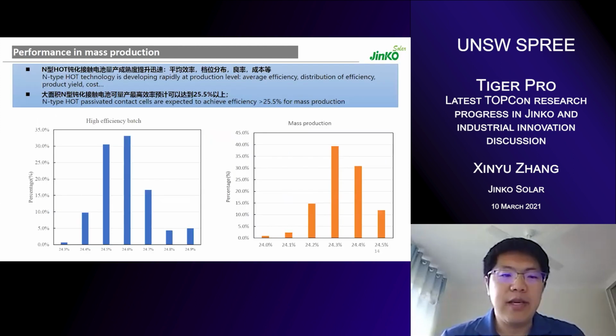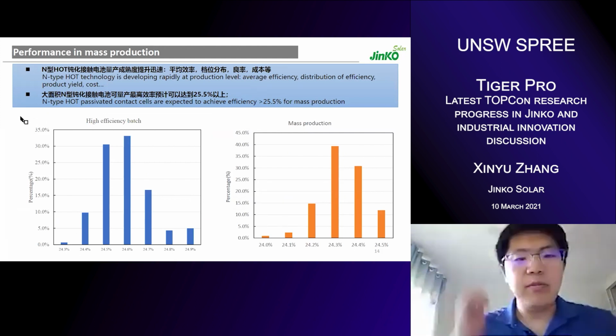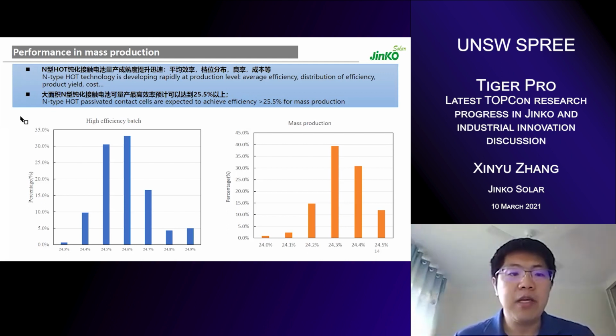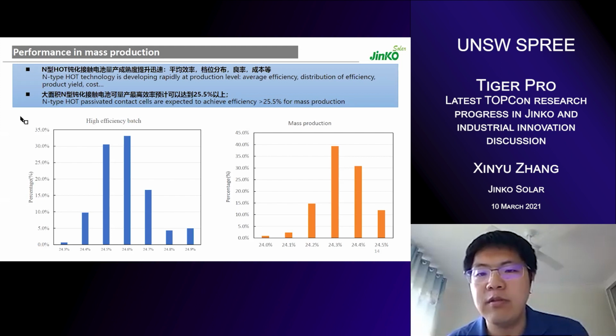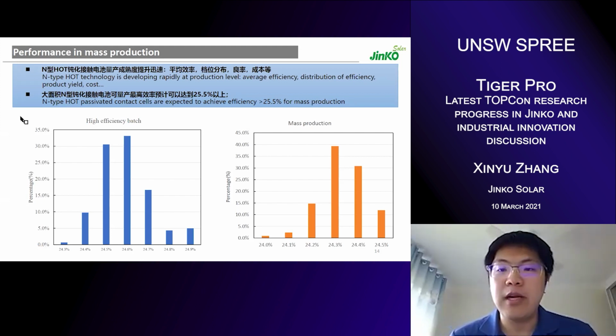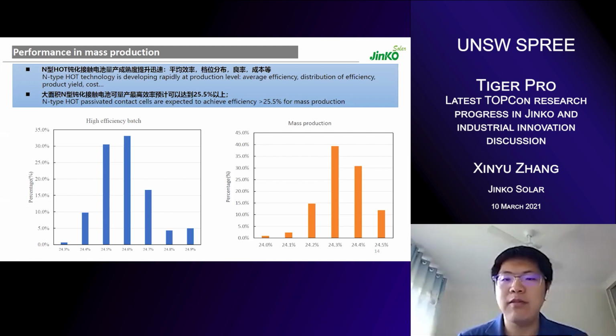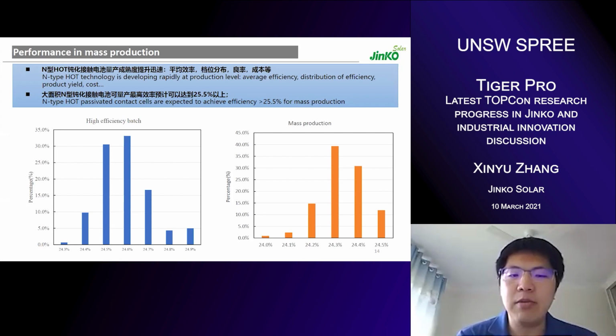Next page. Here we mentioned some of our mass production situation. We have a mass production line, not only one line, but 1 gigawatt of capacity for TOPCon. We have seen that the improvement of the average efficiency, the efficiency distribution, and also the yield rate is improving very fast. Because TOPCon, unlike heterojunction, is a combination of several familiar processes, such as diffusion. Although instead of only phosphorus, now we have both phosphorus and boron diffusion, it is still relatively familiar to the production people. And we have simplified the process flow a lot, so it's only a few steps more than the traditional PERC production line. So everything can be controlled relatively well.